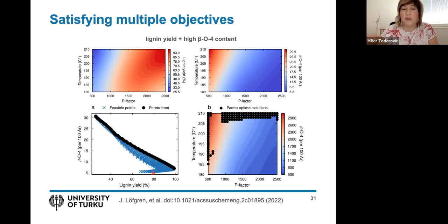So let's say you want to create lignin that has 80% yield, but then we'll have to live with about 10 or 15 units of beta O4. And if you really insist that you need high beta O4, so somewhere here, well, then you're going to make like only 40 or 30% lignin yield. So that's how to read this Pareto front.